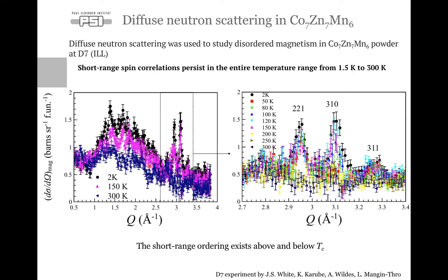And also we see additional magnetic Bragg peaks, additional magnetic contribution to the commensurate Bragg peaks, that are basically the unresolved helical satellites sitting on top of, for example, the 221, 310, 311 peaks that appear below the transition temperature. Otherwise, the diffuse magnetic scattering pattern is the same in the low temperature range.